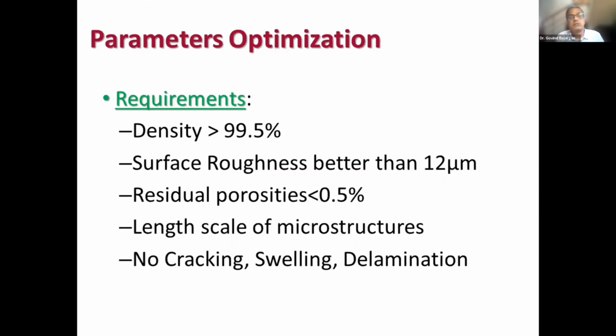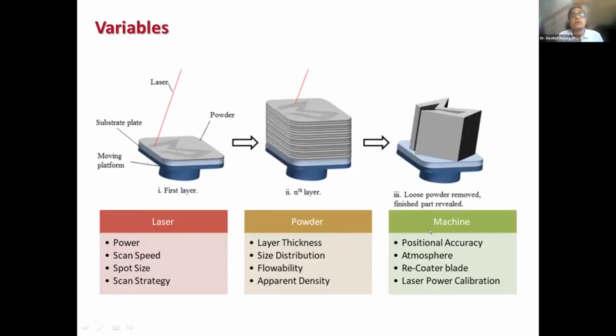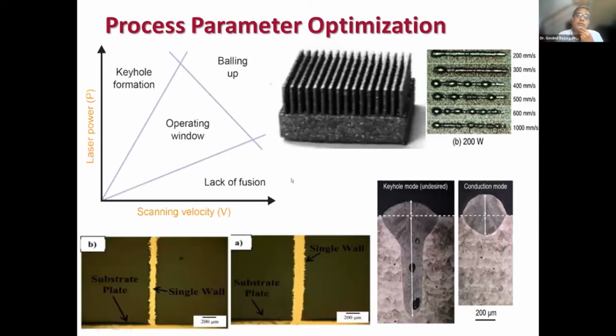The third point was process optimization. Process optimization is a very tricky process, because the requirement we are putting here is generally density of 99.5% or higher, surface roughness of 12 micron or better, fewer porosities, defined fixtures, and no mechanical damage. The process variables, as all of you know, include laser, powder, and machine dependent variables, but mainly the process variables we deal with are the power, scan speed, and scanning strategy, that is hatch spacing and so on.